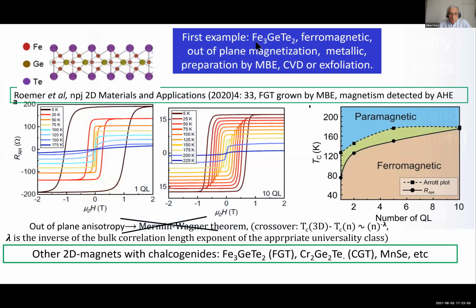A good example of 2D magnets is what is called FGT. FGT is a chalcogenide, which can be prepared by MBE, the best method, CVD or exfoliation, and is a very good ferromagnet. The magnetization in this compound can be detected by the anomalous Hall effect. You can see some cycles of magnetization from anomalous Hall effect for one monolayer on the left, 10 monolayers here. The ordering temperature for this one is about 125 Kelvin, and for 10 monolayers it becomes something like 170 or 180.